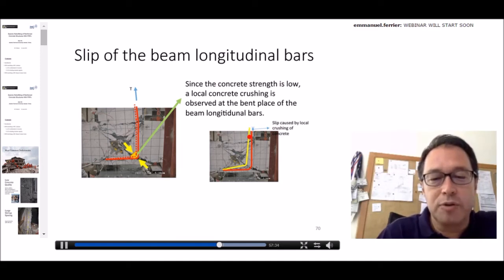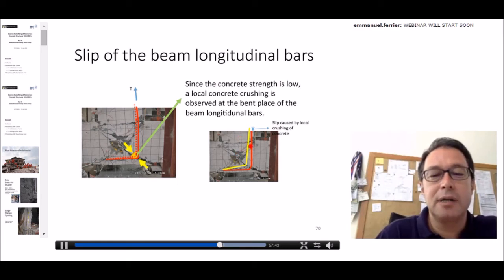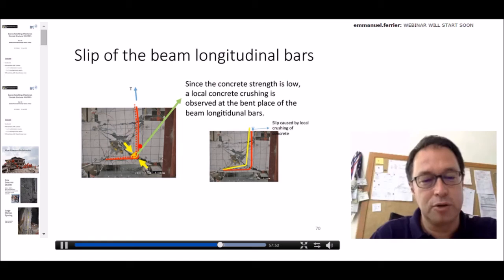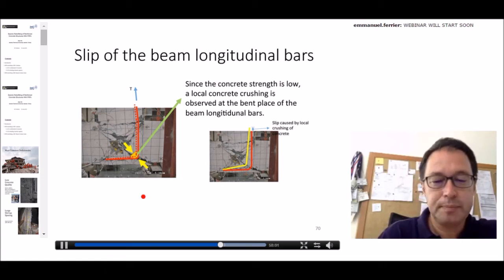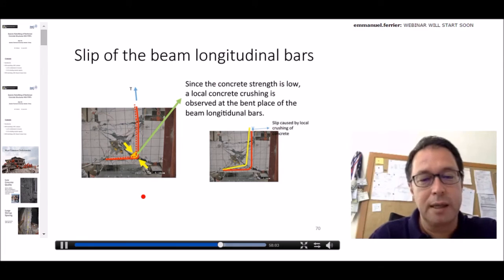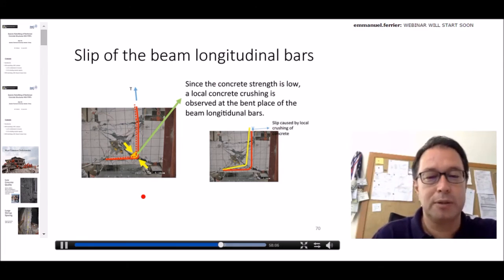So this is reflected by a large crack at the intersection of the column and the beam, and relatively lower strengths than you could reach when the beam longitudinal bars yield. I should say that obviously because of this slip type of behavior, the beam bars were not yielded, even though there was a big displacement at this point. This is proving the mechanism that I want to explain to you.